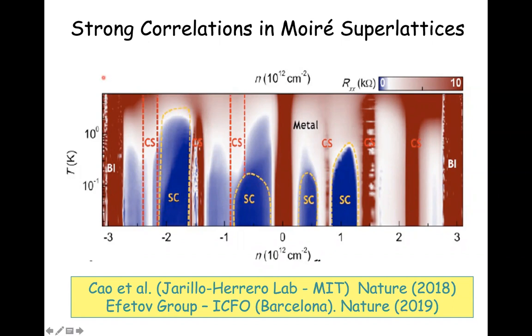So this is a way of making artificial crystals. And it's artificial crystals, as I'll explain, with around 40,000 atoms per unit cell, so big lattice constants. And one of the things that's important about having such big atoms, so to speak, is that you can change the number of electrons per atom just using electrical gates.